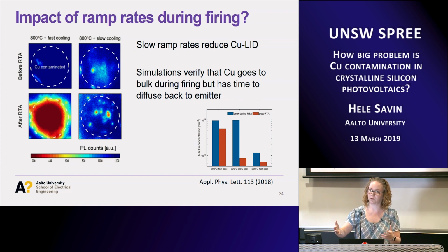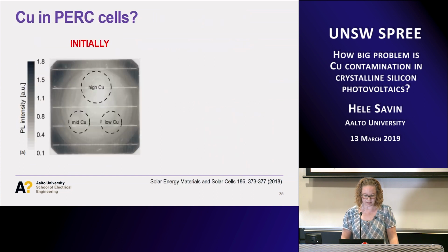But if it's not this very rapid firing after firing, and you do the slow cooling, then you actually have enough time for copper to go back to the emitter, and that explains why these ramp rates will impact the copper LID. And this was relatively easy to also verify by the simulations that this is what we expected to be happening. I will talk about the simulations also at some point.